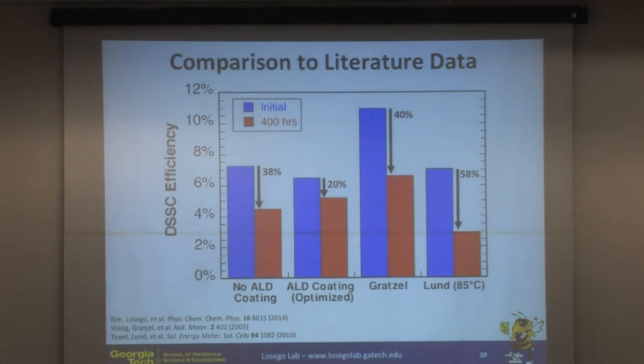So now if we compare this to the literature data, this is our uncoated, our control device. We see almost a 40% drop in efficiency over 400 hours. This is our optimized device with this mixed alumina TiO2. We get about a 20% drop in efficiency. Again, this is true efficiency.